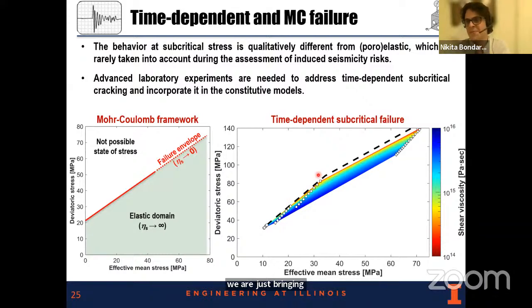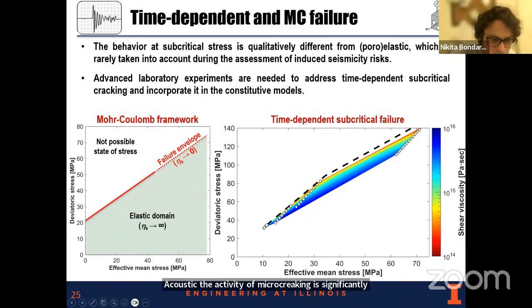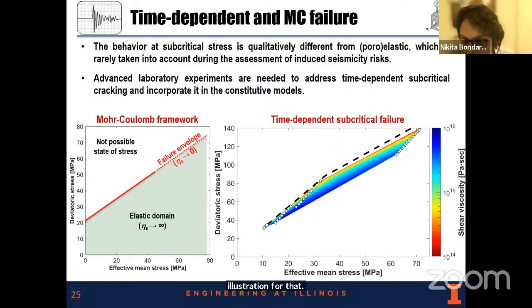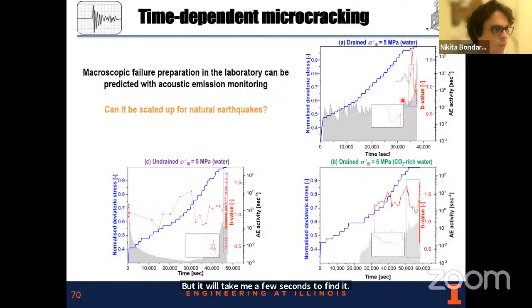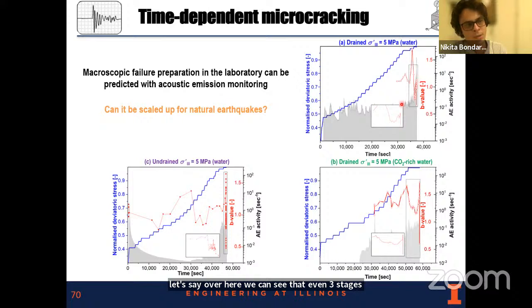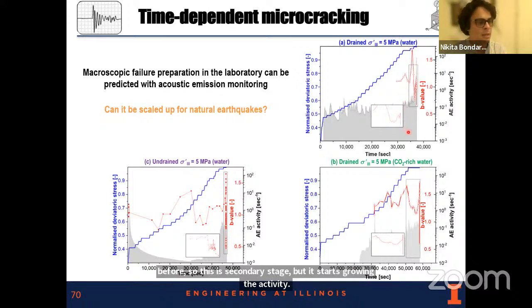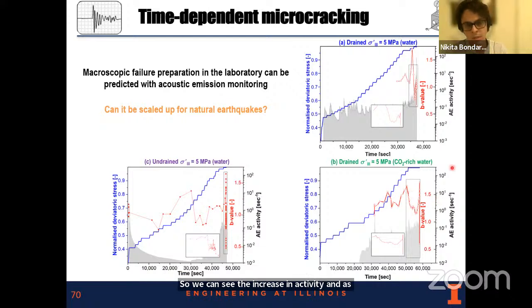So the safest option is to start far away from failure, and after that, go step by step. Acoustic emission is very useful in this case because it's difficult to see the nucleation in terms of the deformation. The activity of microcracking is significantly more sensitive to that. I have some illustration for that, but it will take me a few seconds to find it. Yes. So over here, we can see that even 3 stages before, this is the secondary stage, the activity starts growing. So we can see the increase in the activity and associated b-values there, but we still need to do better characterization of acoustic emission.